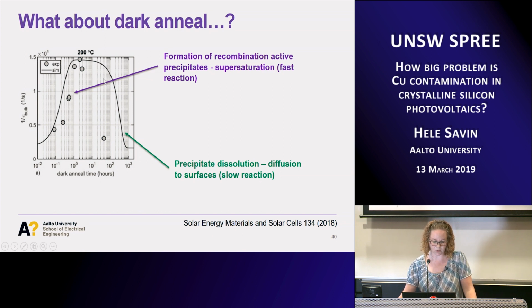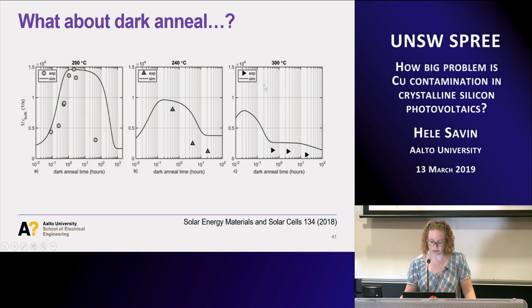Okay, it doesn't exactly match the experiments, but I think the trend is quite interesting, that it is so similar to the experiments. And then by increasing the temperature to 240 or 300, it is slightly challenging to measure these short times experimentally, but with modeling we still see correlation with those experiments. And now these simulations and the experiments we have used to try to find ways to mitigate the degradation, because we would like to have as little amount of precipitates as possible during the light soaking.